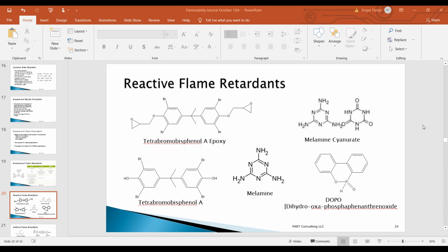On the electronic side, the lower right-hand side, DOPO is one of the phosphorus flame retardant materials. It's been around for quite a while now, about 20 years, as a flame retardant. And it and its many variations are quite common for use in composites and electronics. So they basically incorporate phosphorus into the formulation, and the structure there also forms a very nice char.